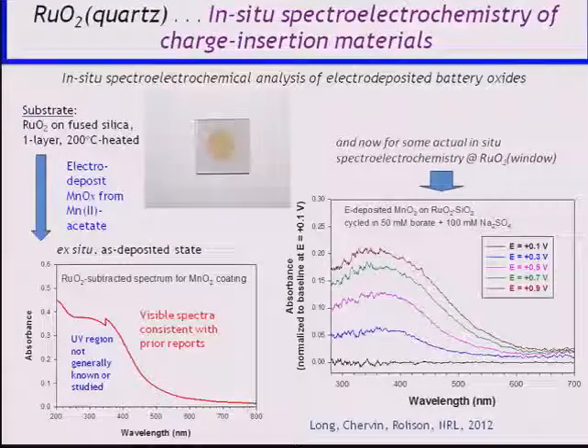So this is what it looks like doing some very early spectroelectrochemistry in this system. So at plus 0.1, you've made manganese 3, and it's colorless. As you take the potential positive and start converting that to manganese 4 plus, it colors. Normally you would be monitoring the color at about 500, so you can see that march up as we get back towards the color center of manganese 4.